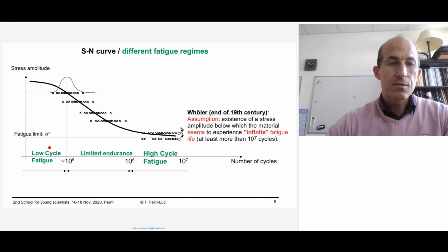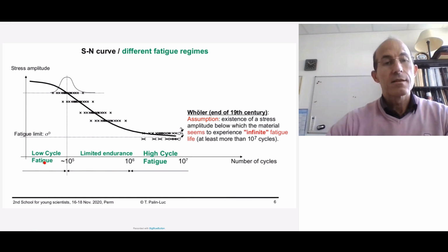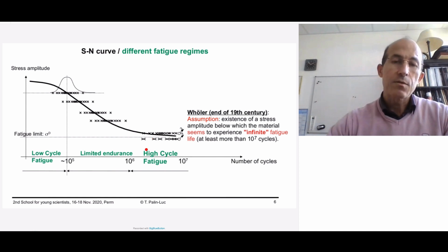The low cycle fatigue domain, where there are macroscopic plastic strains. Approximately, it is up to around 10 to the 5 cycles. Then there is a domain named limited endurance, approximately 1 decade. And then above a few million cycles, there is a high cycle fatigue regime. The high cycle fatigue regime is characterized by a macroscopic elasticity. We will see that in a few minutes.